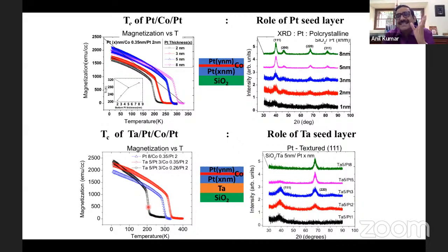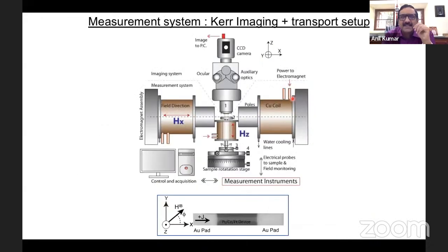I'm looking for TC above room temperature because all the experiments I'm going to show you are room temperature experiments. I don't want to show you low temperature experiments. Also, you see that the magnetization of this material is almost 2000 EMU per cc, whereas you know that bulk cobalt has only 1400 EMU per cc. So where is this additional 600 EMU per cc coming from? We have other experiments which show that this cobalt induces ferromagnetism, a magnetic moment, in platinum, and the platinum moment adds to this magnetization. That's how it is coming. These are all corroborated with high resolution X-ray diffraction studies.